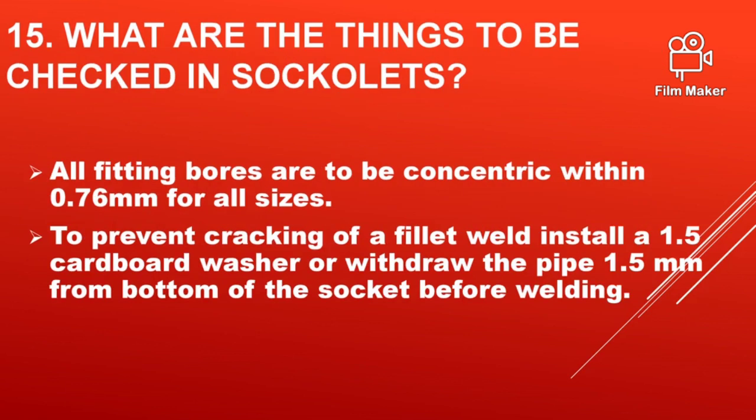What are the things to be checked in a socket weld? That is concentricity within 0.76 mm, and the gap between the bottom of the socket should be 1.5 mm.